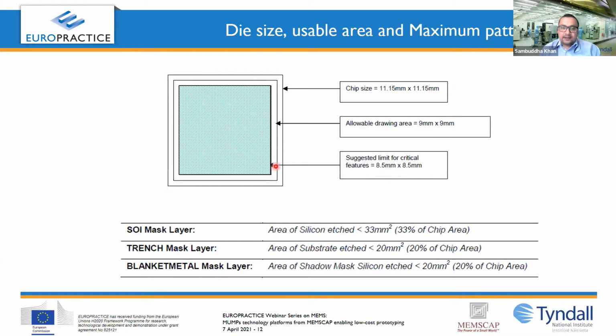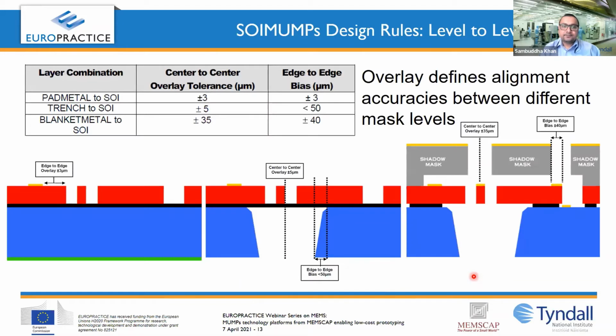Now, there are certain guidelines on how much can be etched. In the total mask, you cannot etch silicon more than 33% of the chip area. You cannot etch trench more than 20% of the chip area. And as well for the blanket metal, you cannot etch the silicon for the shadow mask more than 20% of the chip area.